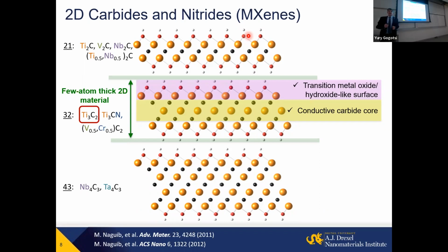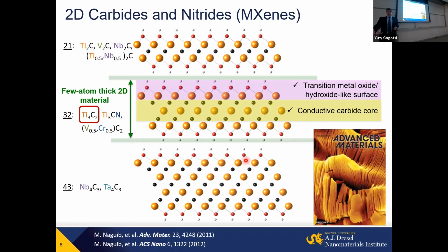And of course, they come in a variety of flavors, as I mentioned to you. We can have different numbers of transition metal, carbon, nitrogen layers. And also, we can have different surface termination. And Michael Naguib, a PhD student who worked with myself and Michel Barsoum, who was the first discoverer of this material, reported during his PhD study a dozen different new MXene compositions here. Moreover, we can not only have different transition metal, carbon, nitrogen, but can make a solid solution on the X side, carbonitride. We can make a solid solution on the M side. So we have a huge number of materials.